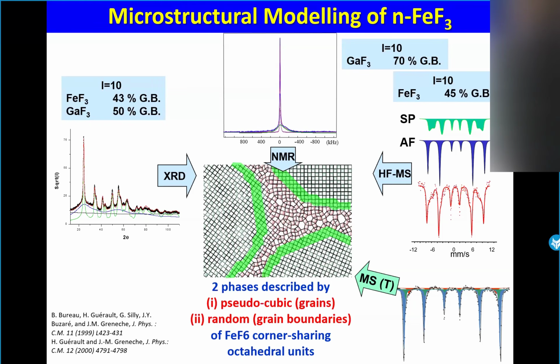So the problem now is to read what about the information. When you are playing with nanostructured powders, what is the limit for X-ray diffraction? What is the limit for a local probe technique? And of course, if you look, for example, here, this component, green colored, belongs to the grain when you are considering X-ray diffraction. But when you are considering some local probe technique, this component belongs to the grain boundary because there was some distortion. Here is a schematic view.